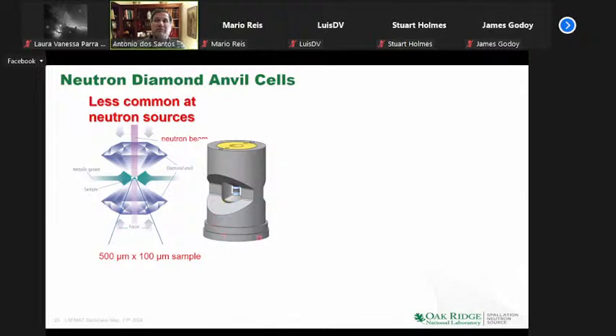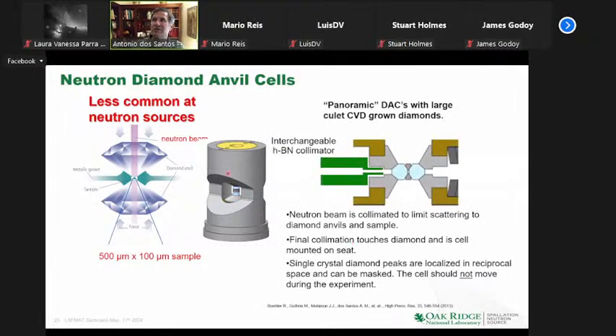You can see it's very beefy, and because of this large culet, you really need a press to increase pressure. You can't do it with screws anymore. For scale, this is about 5 centimeters, and this is maybe 8 centimeters tall. So this would fit in your average coffee cup, at least an American coffee cup. The way we measure is through the axis, and the beam goes through the diamonds and scatters at 90 degrees, unlike with X-rays.